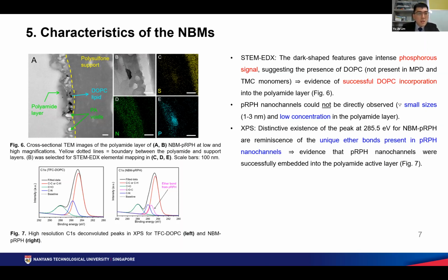In short, the results in figure 6 are a good evidence of the successful incorporation of DOPC liposomes into the membrane selective layer. However, because of their small sizes and low concentration, the PRPH nanochannels were not directly observed in the TEM images. In an attempt to prove that the PRPH nanochannels were indeed successfully incorporated into the polyamide selective layer, we used X-ray photoelectron spectroscopy, XPS, to compare the TFC membrane made with virgin DOPC liposomes and the NBM membranes made with PRPH liposomes.